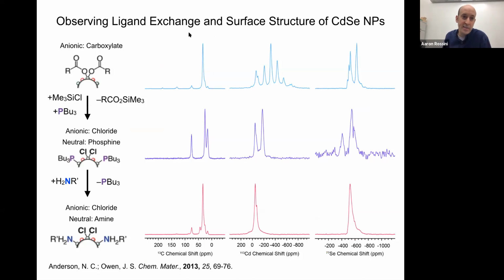This is new data that's unpublished and is something we're working on right now. So what I'm showing you here is some DNP enhanced NMR spectra of cadmium selenide nanoparticles. We've got carbon NMR on the left, the cadmium-113 NMR in the middle and selenium-77 on the far right. So this is for a series of ligand exchange particles.